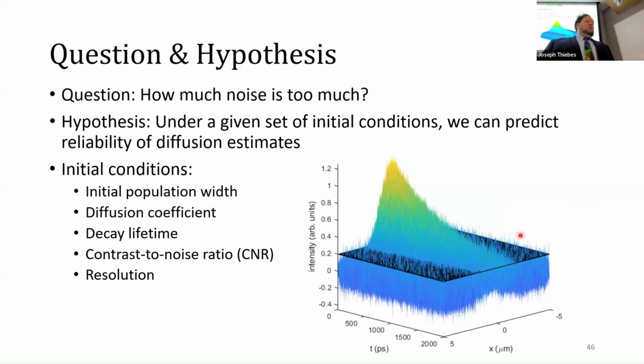So we start with an initial population width and an initial diffusion coefficient that we're just going to assume is true, and we plug that into a simulation to create noisy Gaussians. We also come up with a decay lifetime and an initial contrast to noise ratio. How much noise is there at the beginning? And then the resolution of our instrument: do we have 100 pixels across? Do we have 500 pixels across? And then how many time frames do we take, and over how much time? Using those initial conditions, we can try to predict how the noise is going to impact our measurements. And this was an early simulation I did just as an illustration.